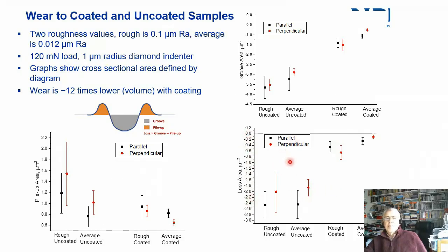What I didn't say was we carried out experiments parallel to the lay of the grinding, in other words, parallel to the grinding marks, and also perpendicular to the grinding marks. And frankly, although you might say there's a little bit of a difference here, with less damage, sorry, in the perpendicular direction, there's not much of a difference, so I wouldn't think that's terribly significant.